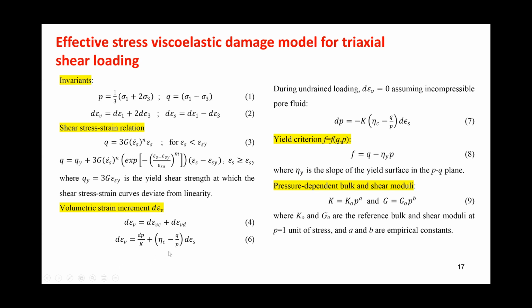So, okay, when Q over P is less than eta sub C, then this is a positive volume change, which means it's compactive. But when Q over P exceeds eta sub C, then it is negative, meaning it's dilative. If we set dε sub v equal to 0 and solve for dP, this is the change in the mean stress during undrained loading.